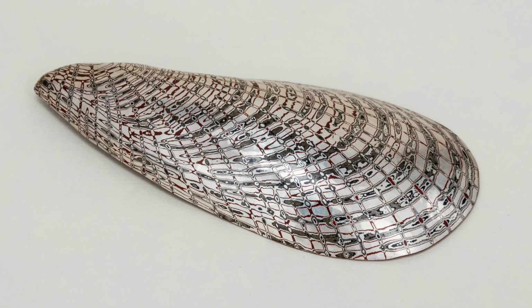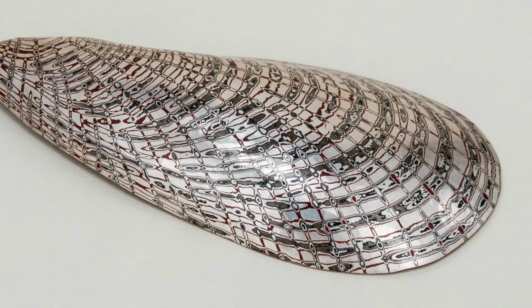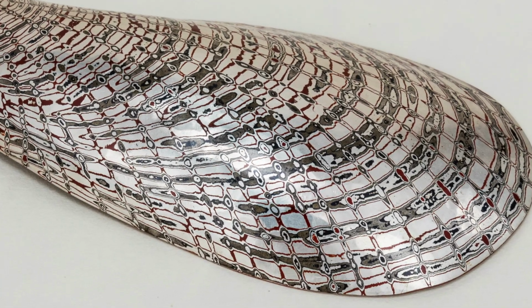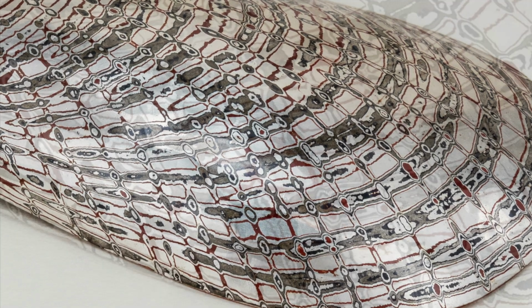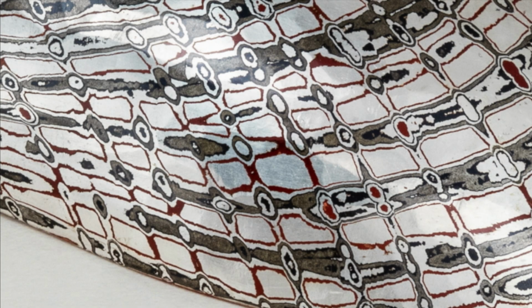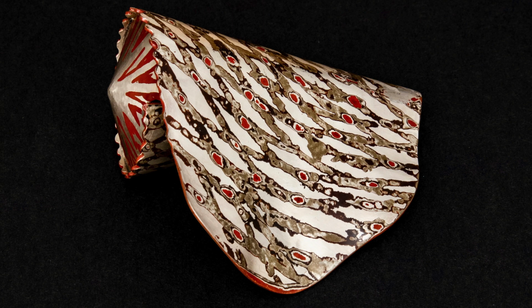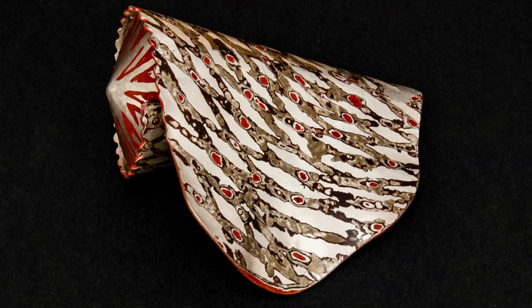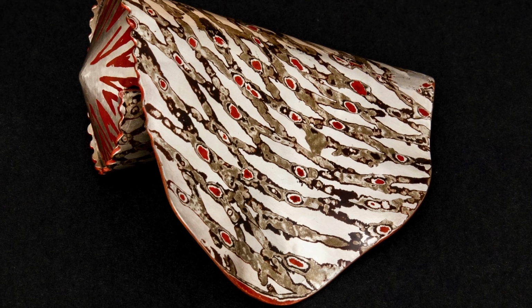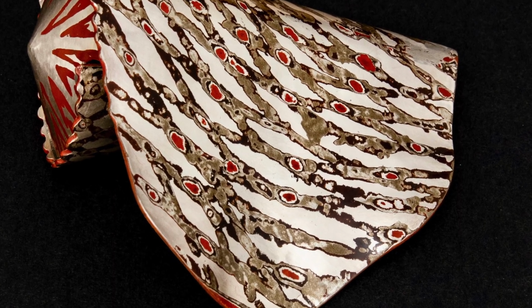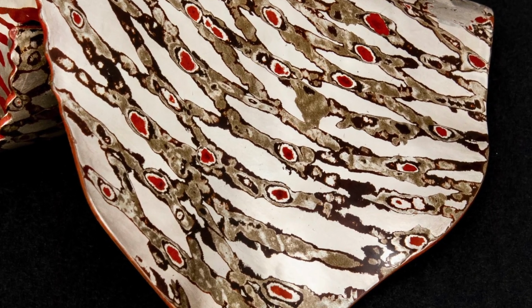Here, the deep wide channels stop at the deep gray layers. The bullseye shapes dive into the black or dark layers. A few even cut into the red copper core. This conch shell has a silver surface with curving channels meeting at acute angles. The crossing areas show a very deep copper red layer, which is a 6th layer down, and a hint of a dark layer below it.